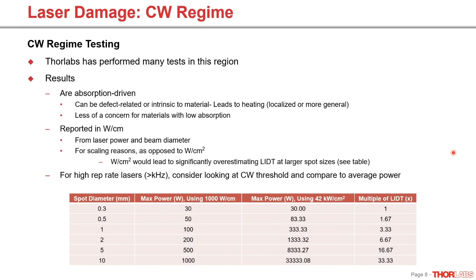Next we have the CW regime, where we have performed a variety of tests. And in the CW regime, results are typically absorption driven. So this absorption can be either defect related, because again, I'm sure you can imagine some of the particles that I mentioned on the previous slide, whether they're from polish or from inclusions in the coating, will be less robust than what's intended to be there. But this can also be intrinsic to the material.